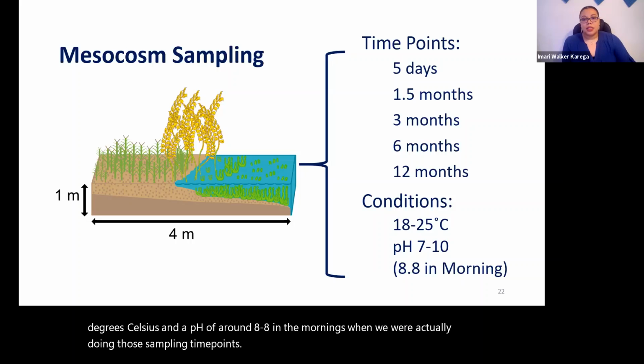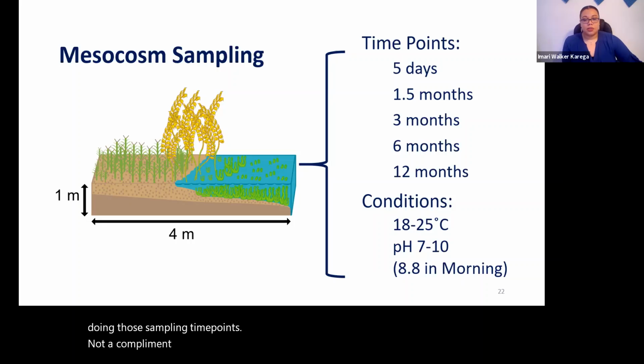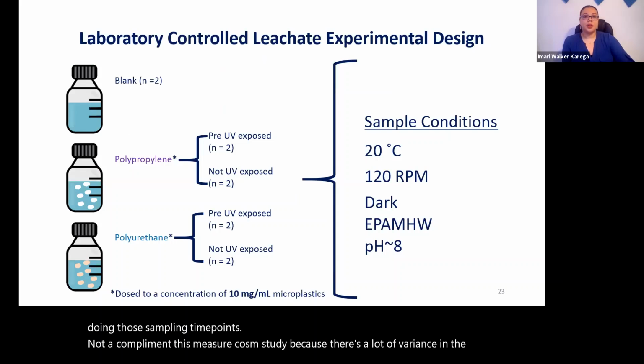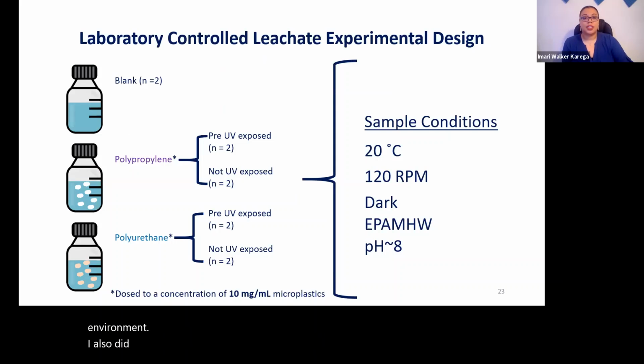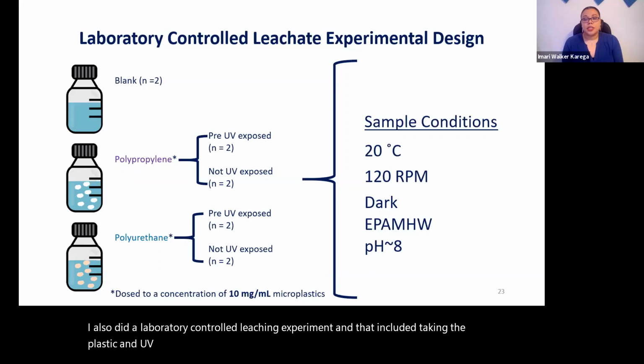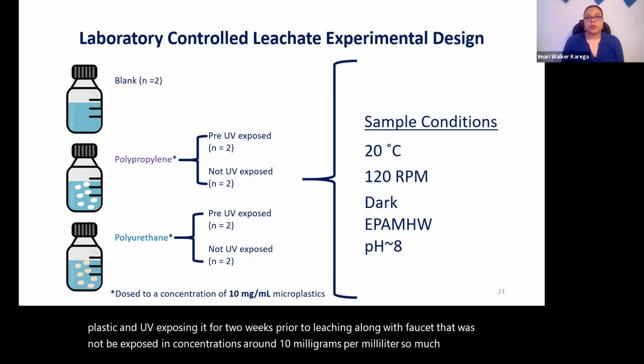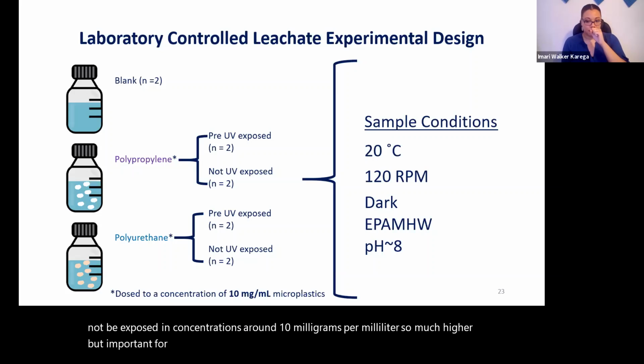Now, to complement this mesocosm study, because there's a lot of variance in the environment, I also did a laboratory controlled leaching experiment, and that included taking the plastic and UV exposing it for 2 weeks prior to leaching, along with plastic that was not UV exposed, in concentrations around 10 milligrams per milliliter, so much higher, but important for direct injection on our instrument.